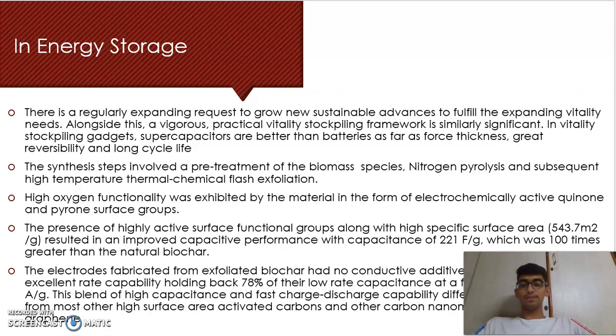The synthesis steps involved a pre-treatment of biomass species, nitrogen pyrolysis and subsequent high temperature thermal chemical flash exfoliation. High oxygen functionality was exhibited by the material in the form of electrochemically active quinone and pyrrole surface groups. The presence of highly active surface functional groups along with the high specific surface area, which is 543.7 meter square per gram, resulted in an improved capacitive performance with a capacitance of 221 farad per gram, which was 100 times greater than the natural biochar.